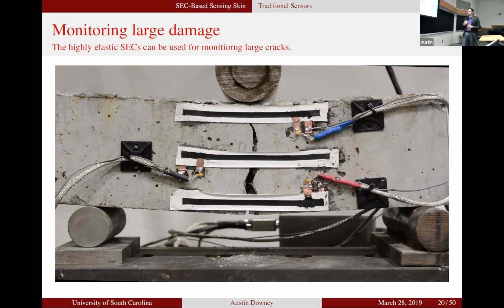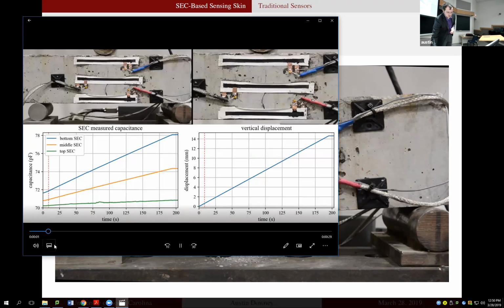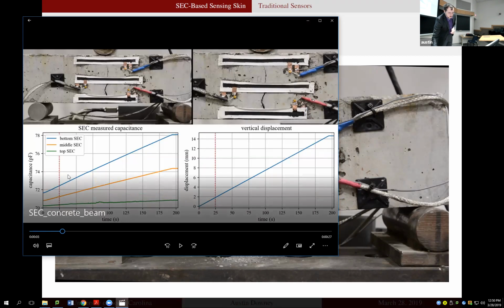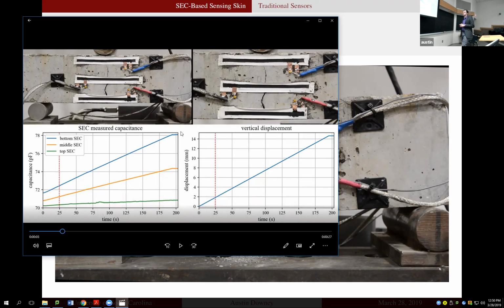When these cracks get quite big, sometimes you have a glue that will stick over a gap. And we were trying to get our nice, clean measurement signals. For smaller measurements, gluing it all the way across is definitely more advantageous because we'll start to get every small variation. But when you want these nice, long, clean signals, that's more like an LVDT. Gluing it on the edges is a much more appropriate response. So for smaller cracks, we have found that gluing completely tends to help. For these larger cracks, gluing completely will get you lots of ripples that are just a function of the glue cracking and not so much of the actual expansion of the joint. And so it definitely needs some more investigation.